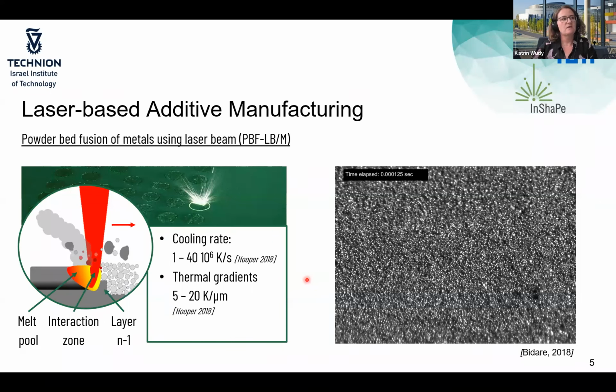What we have done in our investigations is now what you can see here is the intensity distribution of a Gaussian beam profile with a high intensity, red, in the middle and less intensity, blue, in these outer rings. And what we have conducted is we used several ring-shaped beam profiles, and you can change these ring-shaped beam profiles on the fly in microseconds during processing. And there are several ring-shaped beam profiles available, starting from this one with the index 1 to the index 6.